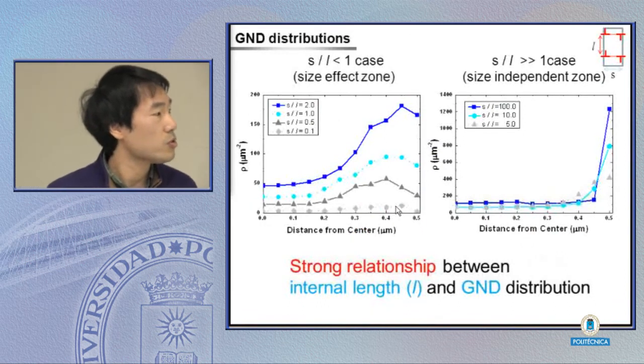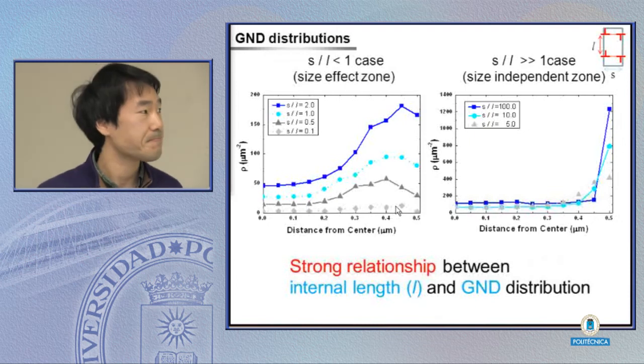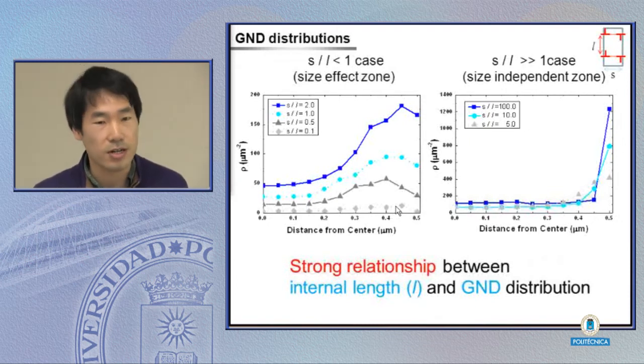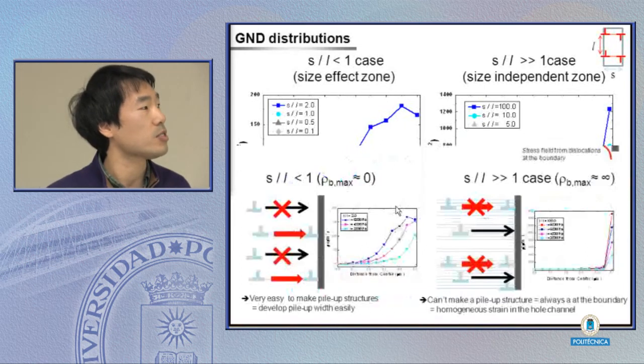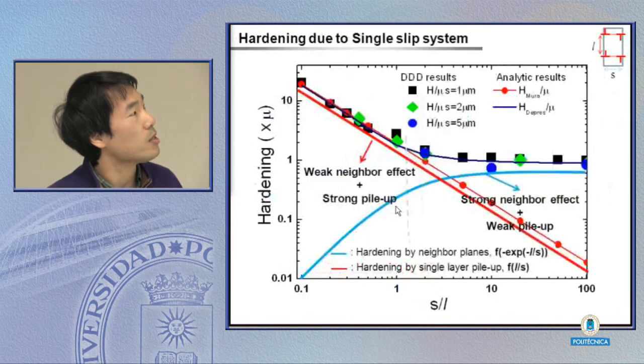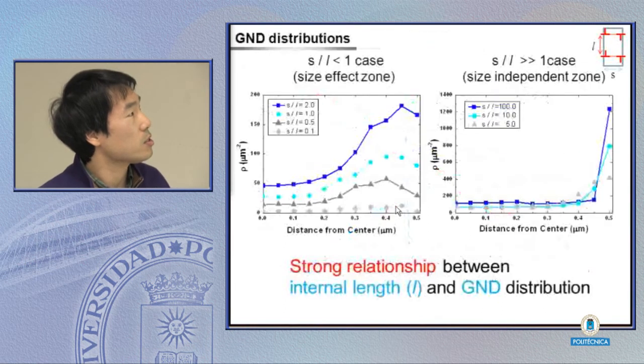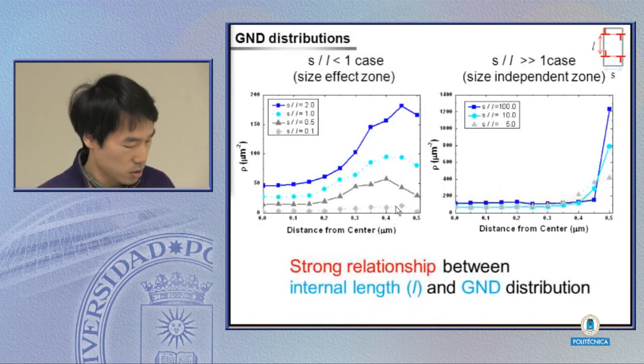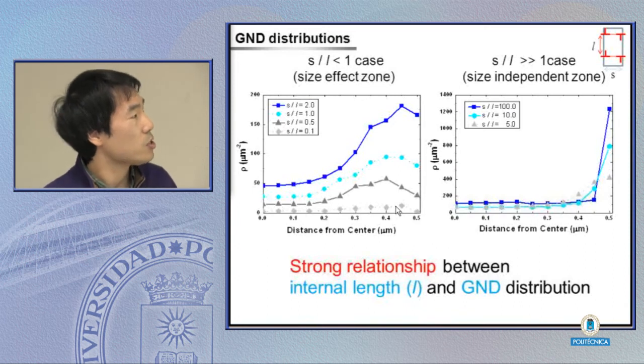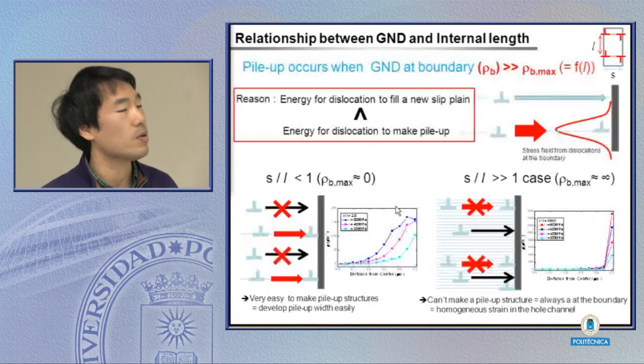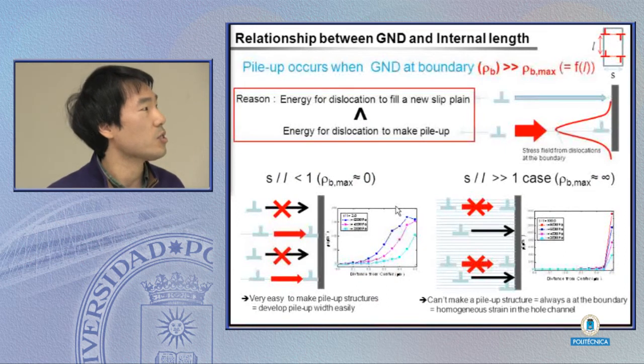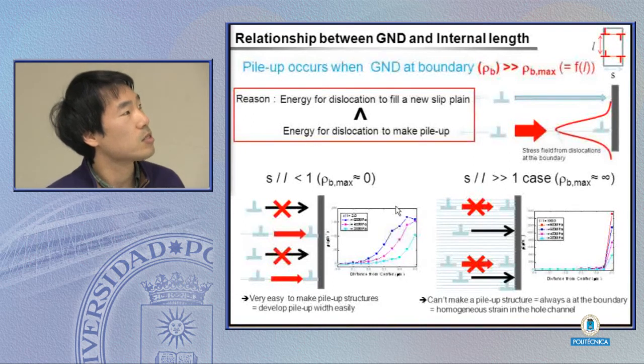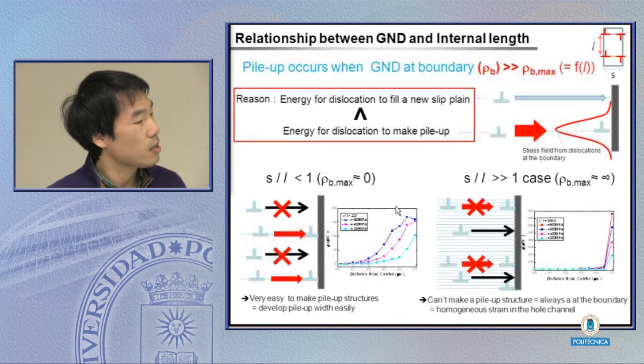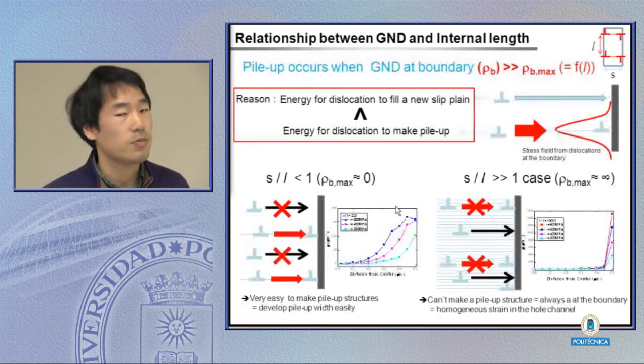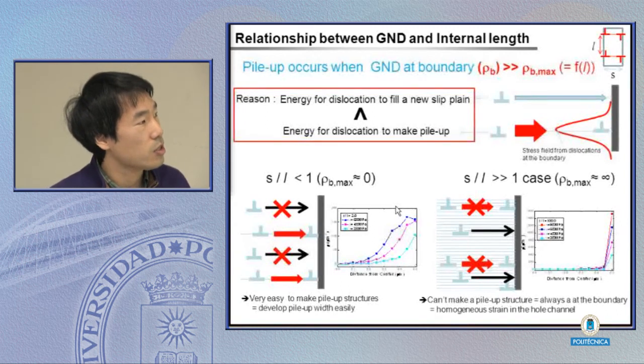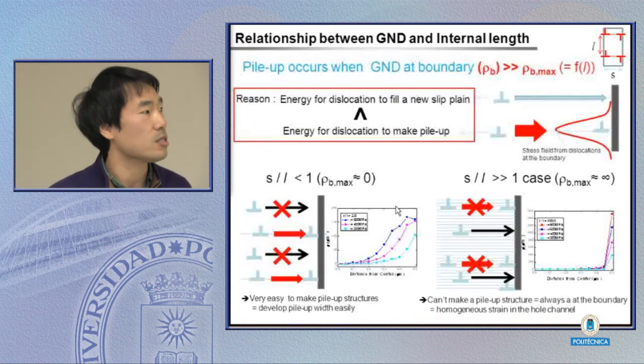And we can show you the GND distribution inside the crystal. Here also totally depends on the ratio between two length scales. When the ratio is smaller than 1, here is the size effect zone, right, in this case. In this case, the GND density is minimum at the center and maximum at the boundary, and it increases gradually. However, when the ratio is very big, as the non-size effect zone, in this case, the distribution is only accumulated at the boundary, not in the bulk crystal.